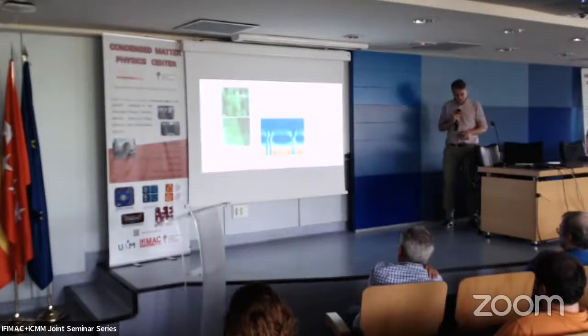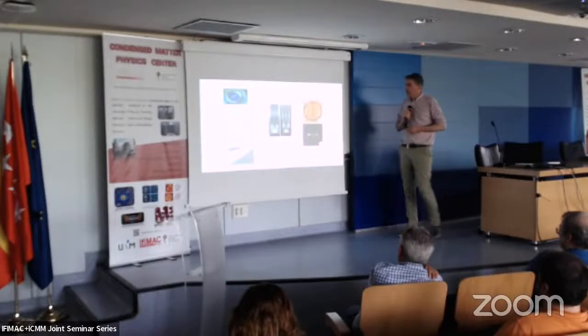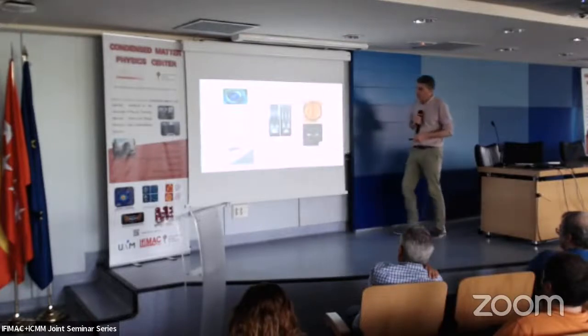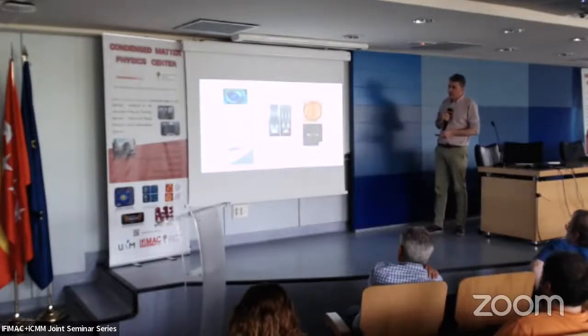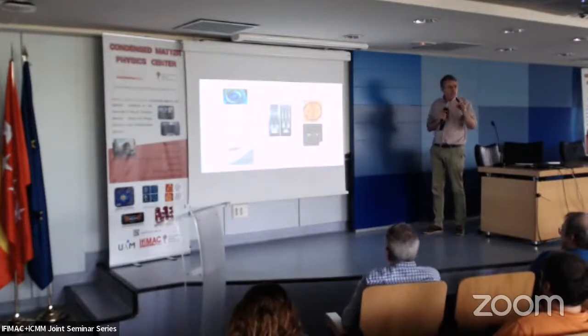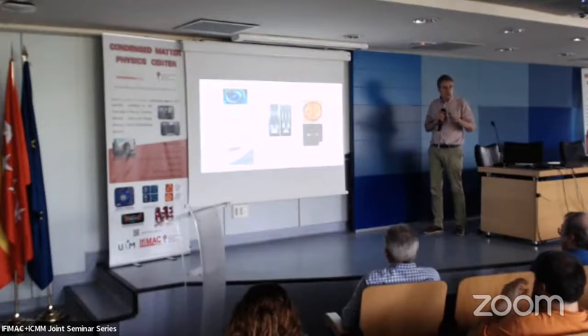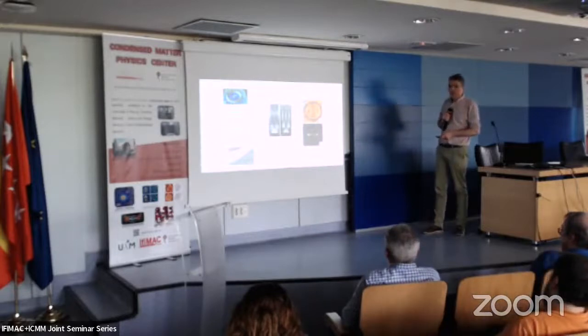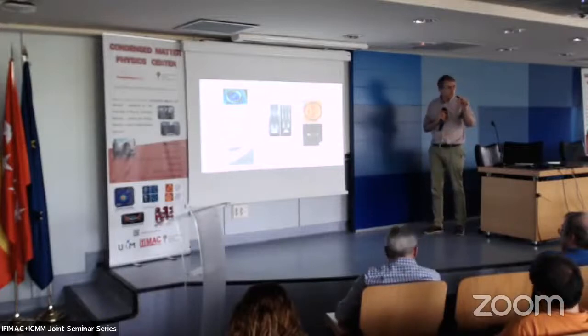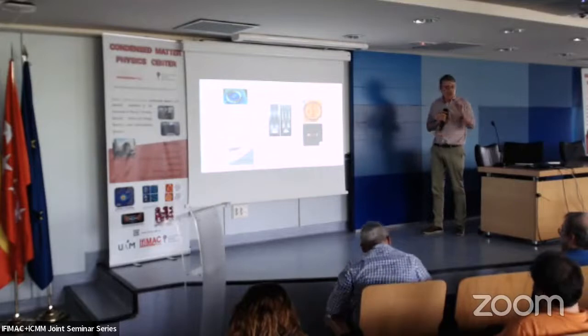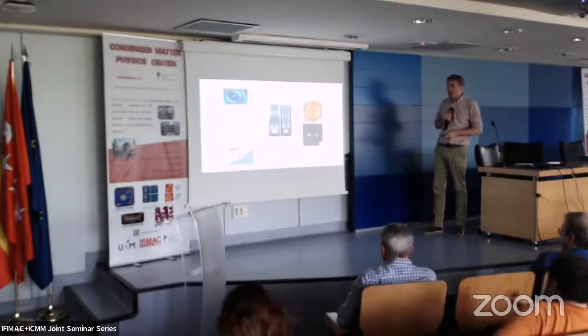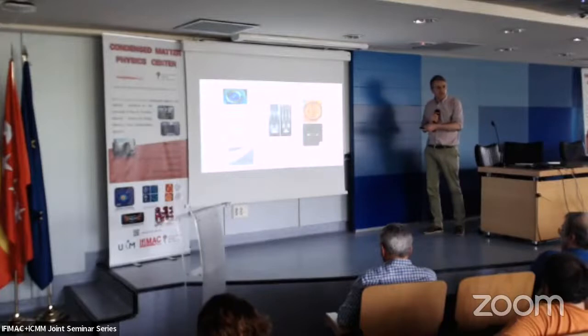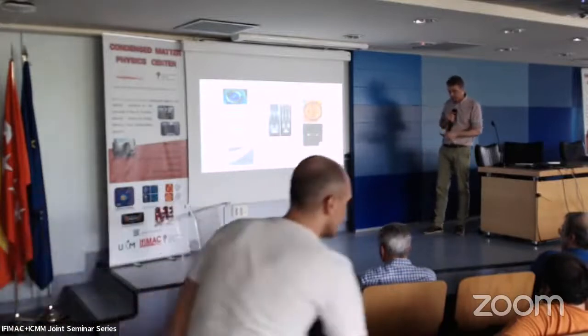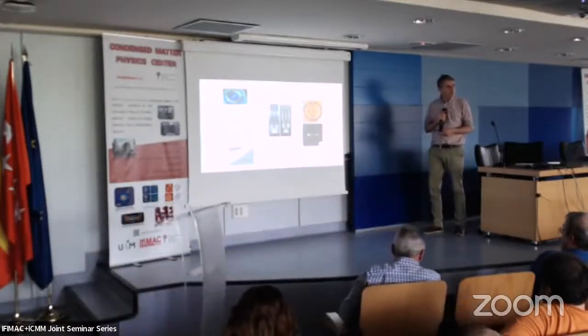So what we have found here is actually a consequence of quantum confinement, but it is a very peculiar quantum confinement. Here you see that we have confinement, okay? So we have different levels, and you see that these levels have a certain width. They have a certain width because they are sensing the electronic correlations inside the bulk. And this gives this width here. So by making very long terraces, we could make the difference between the quantum levels very, very close to each other. And then we could eventually match to superconductivity and see what happens there, and see if this may change the superconducting properties, as I have proposed earlier.